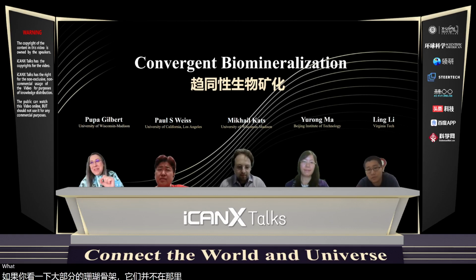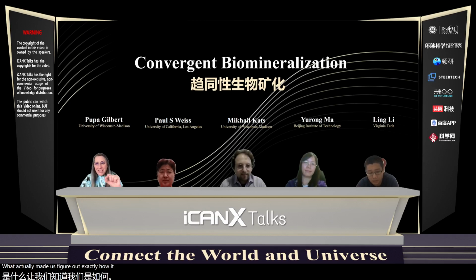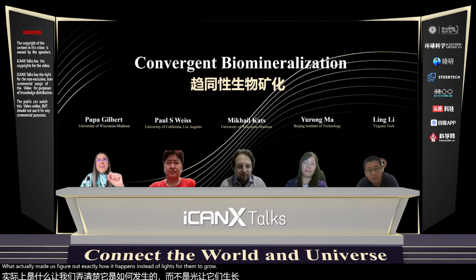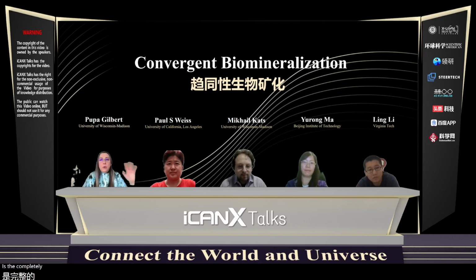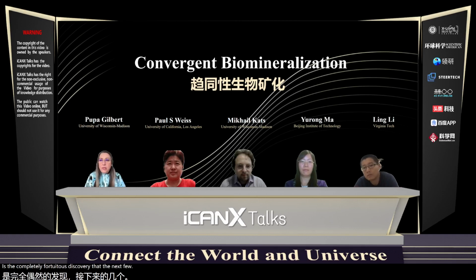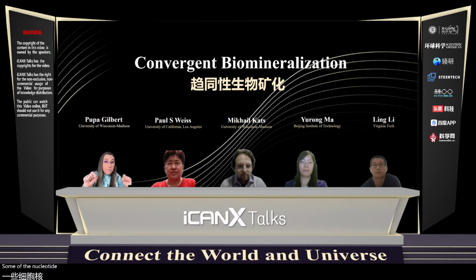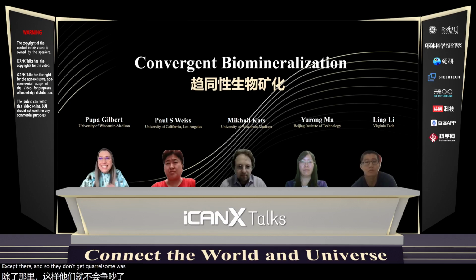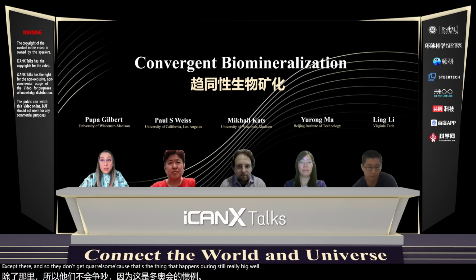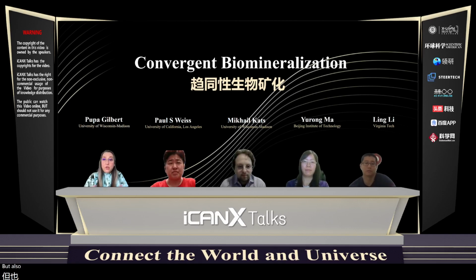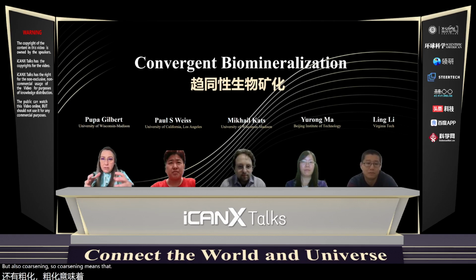What actually made us figure out exactly how it happens in spherulites was the completely fortuitous discovery that in a few species of corals, for reasons we don't really know, some of the nuclei that are misoriented stay. Probably they are kinetically trapped. There's some organic that keeps them there, and so they don't get coarsened, because that's the thing that happens during spherulitic growth. Not only acicular, but also coarsening. So coarsening means that bigger crystals grow bigger at the expense of the smaller ones.